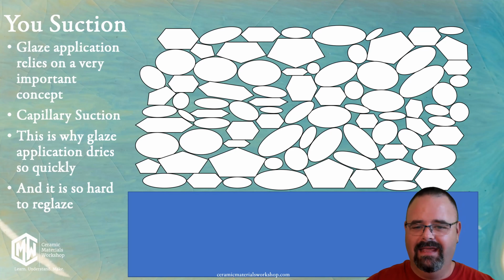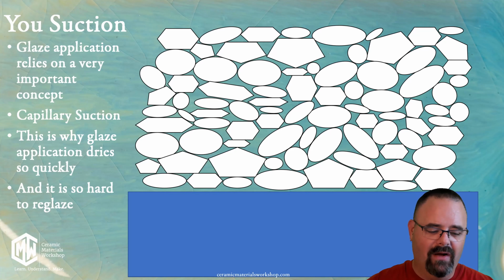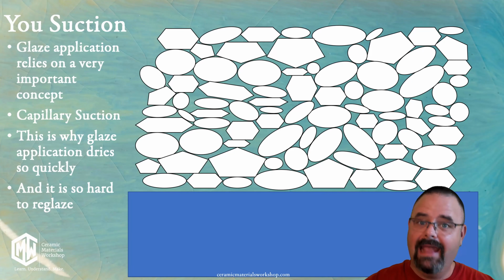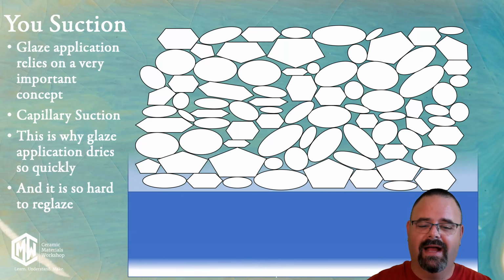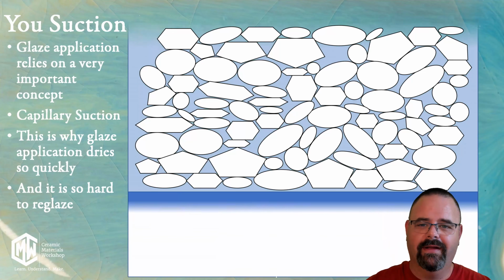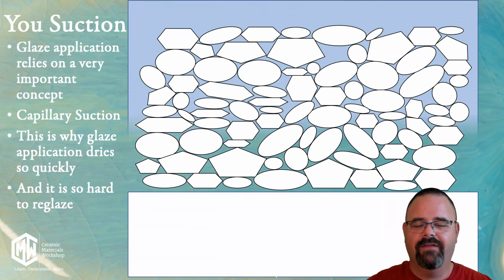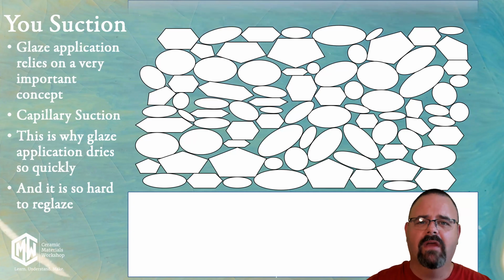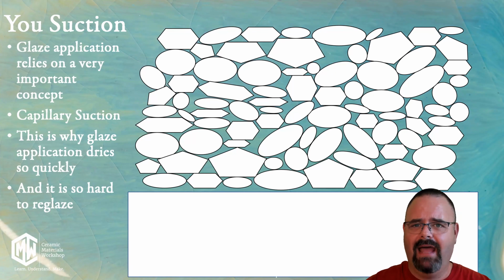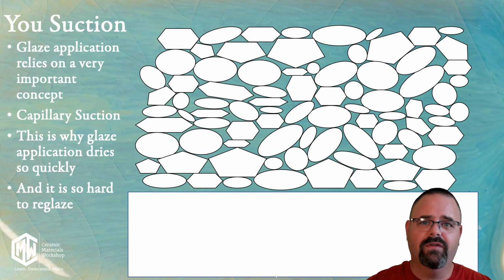Okay. Now, this is really, really important because now the water is there inside that bisque and not in the glaze, but that doesn't mean we don't have to get the water out. Of course, the water does dry eventually by becoming water vapor and rising back out to the surface and eventually going out to the atmosphere. But this is a process that happens rather quickly and you just never see it happen. Usually it'll happen soon inside the firing as soon as you turn on the kiln or if you let it sit around for a while before you put it in the kiln. But it is the capillary suction that is important because that is what is drawing the particles to the surface.